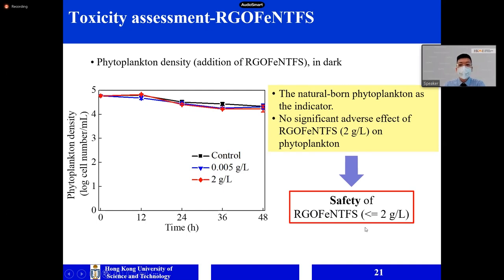One thing I would like to mention is that the dosage here is not the dosage we use in the treatment process, because after treatment, a magnetic separation will be performed to remove up to 99.5% of the photocatalyst. So the residual photocatalyst in the treated sewage is much lower, even much lower than 0.005 gram per liter. Here, 2 grams per liter, we just show the extreme case that if the magnetic separation fails and all of the material in the sewage were discharged to the ocean.